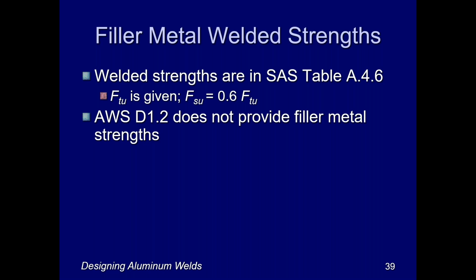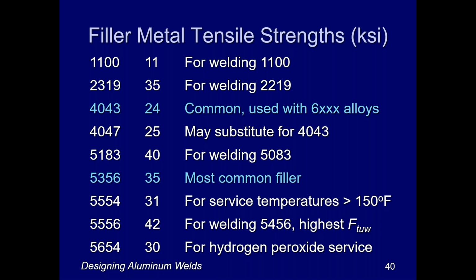Now, that's the base metal. For the filler metals, their welded strengths are given only in the specification for aluminum structures in table A46. They give the tensile ultimate strength there, and they say that the shear ultimate strength is just 60% of the tensile ultimate strength. D1.2 is totally silent on filler metal strengths, and so you've got to get them from the specification for aluminum structures, and I summarized those strengths here in this chart.